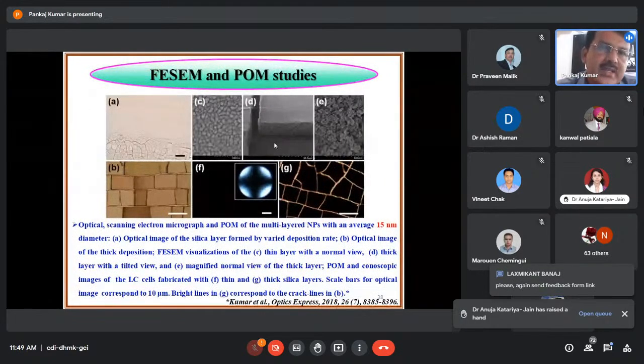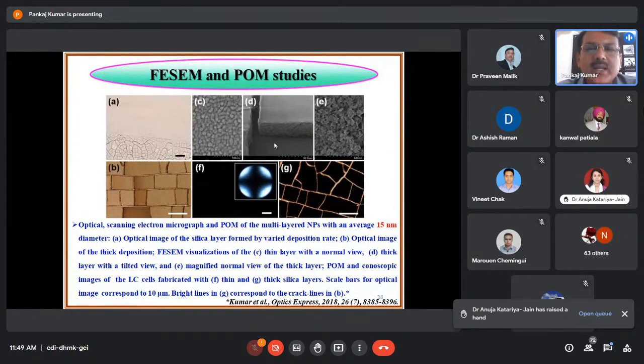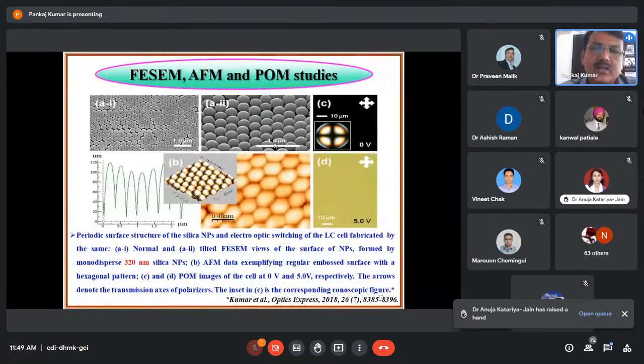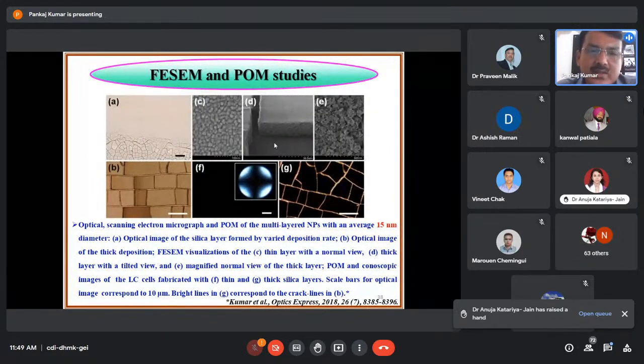So again here you can see FESEM and POM studies: scanning electron micrograph and POM of the multi-layered nanoparticles with an average 15 nanometer diameter. In the previous slide, the silica nanoparticles were 320 nanometer in size. Here the nanoparticles are 15 nanometer in size. So I would like to say that sizes from 15 nanometer to 300 nanometer are all okay, and they can be used for display purposes for making different alignments, meaning vertical alignment of liquid crystals.